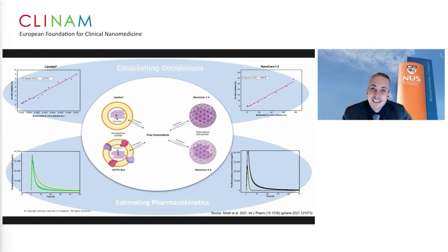But what we still can say is that even if you now find an extracellular vesicle which circulates for 1,000 hours, probably you will not measure drug concentration for more than 50 hours in the bloodstream, because the release behavior is still simulated in a valid way in our assay. And that basically means that because the drug release will be too quick, you probably have then an empty carrier which circulates for 1,000 hours. And that would be a problem in development.